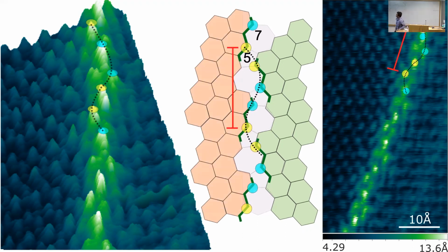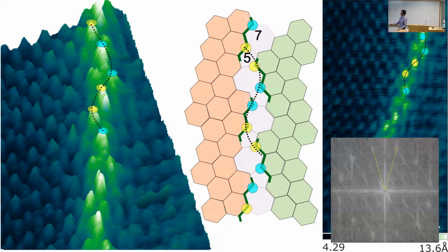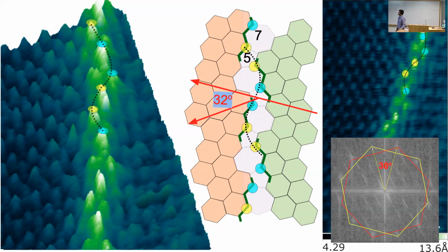So there are other parameters that it has to fit. For example, the periodicities of this zigzag structure have to match, which they did. And the twist angle, the rotation angle at which these grains are rotated. Now, usually whenever you take pictures of atoms, it entices people in the crystallographic community to view it in reciprocal space. So whenever you take an FFT of these two hexagonal grains rotated at any angle, you can see two hexagons that are rotated. And you can measure the amount of rotation angle, and that will turn out to be the same as this rotation angle.